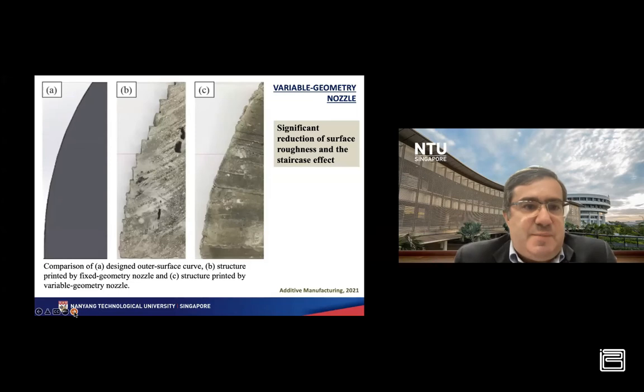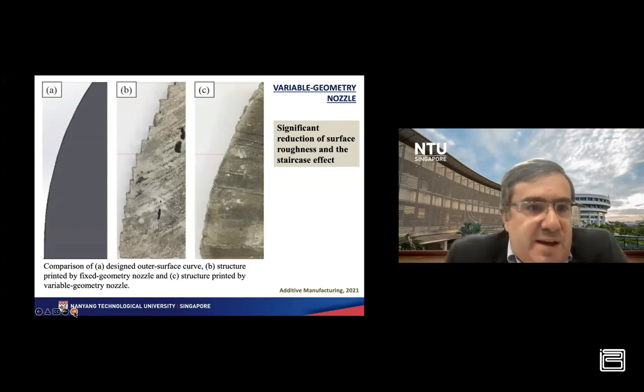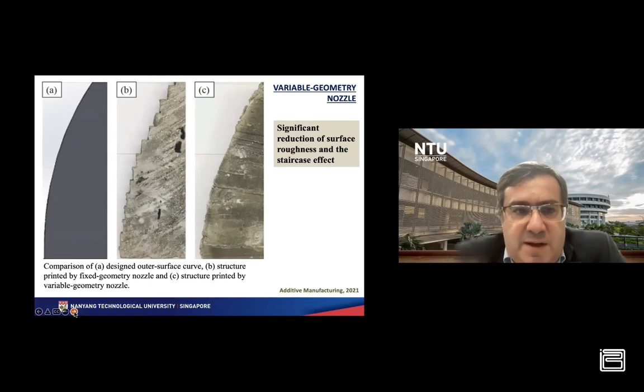We tested the printing head, and this slide shows some of the results using our new printing head with a variable geometry and a standard printing head. And as you can see, with this printing head we were not only able to significantly reduce the staircase effect, we practically eliminated the staircase effect, but it was also possible to significantly reduce the surface roughness.